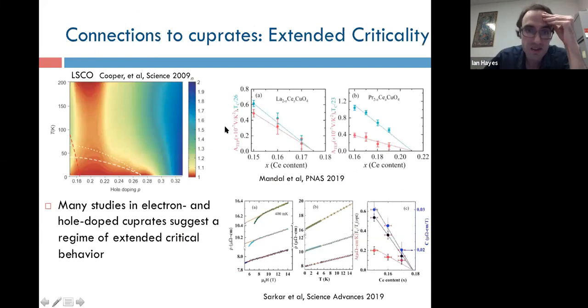Then the next thing I want to point out is that this sort of extended range of critical behavior at low temperatures actually draws barium-122 into closer parallel with a number of cuprates which show some sort of extended critical behavior on the overdoped side. So there are a number of materials that show T-linear resistivity at low temperatures. LSCO has been shown to do so through high field measurements.